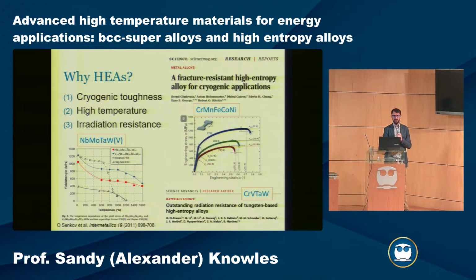If we look instead at this refractory high entropy alloy, where we have niobium, molybdenum, tantalum, and tungsten, we're also seeing higher strength in this system than any of our refractory metals in isolation and higher than nickel-based superalloys. So again, we have a new design rule for designing for high temperature strength. And in this last system, we're talking chromium, vanadium, tantalum, tungsten.